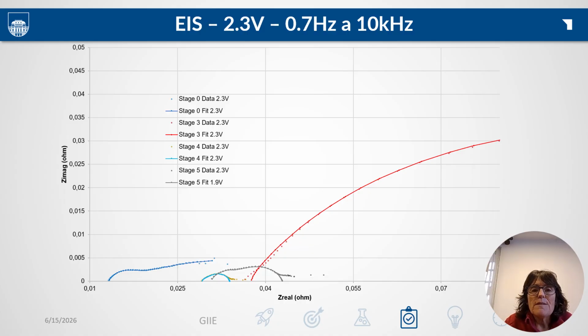This slide presents the overall trend at 2.3 volts, and here we can see the low frequency mass transfer feature that grows substantially with degradation, especially after stage 3, and decreases markedly after the regeneration treatment.